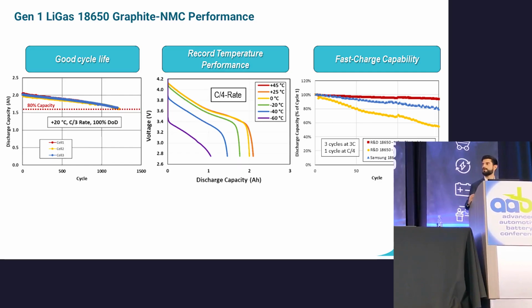So last year I was up on a similar stage at AABC presenting on our Gen 1 LiGas electrolyte chemistry and all the good performance there. On this plot I'm showing just the cycle life on our Gen 1 chemistry, out to about 1,200 cycles at 100% depth of discharge. Pretty good performance for a brand new electrolyte chemistry.